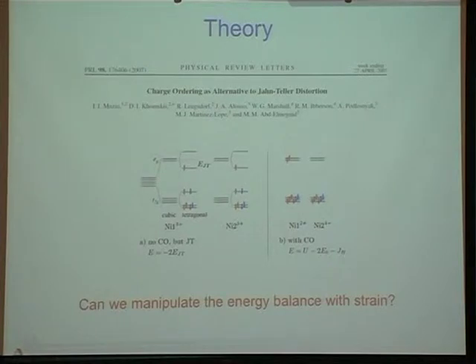But the basic idea is it could either, as an eg1 system, Jahn-Teller distort, and gain by doing that distortion, or it could charge order, and it turns out that nickelates have a very strong propensity for what's called a breathing mode distortion. That is, the octahedra can change size. And you can actually gain a lot of energy through that breathing mode.